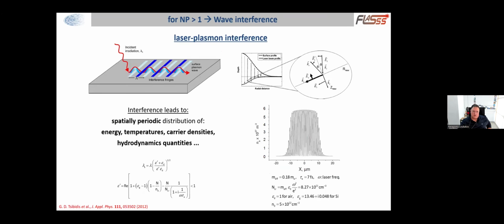When we shine more than one pulse on the same surface, then we have a very interesting phenomenon. The second laser pulse falls onto the heavily structured, rough morphology of this surface, and there is a wave scattered that travels along the material surface, the surface plasmon wave. And this surface plasmon wave interferes with the laser pulse itself, which originally created and excited this surface plasmon. So the result of this laser plasmon interference, taking of course into account the wave calculus, leads to a spatially periodic distribution of various quantities such as energy, temperatures, carrier densities, hydrodynamic quantities, and so on.